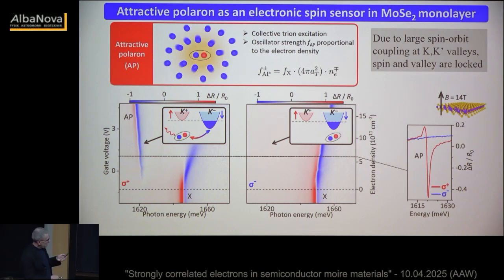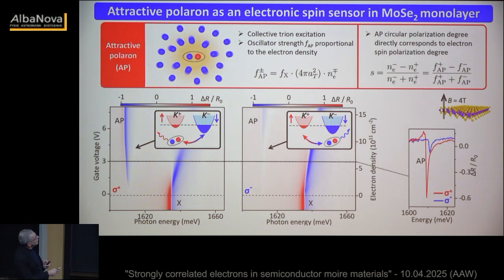There's some interaction with the electrons, but there is no bound state and there is no attractive polaron resonance. Okay? Now, if I didn't go up to such a high field, then, say in this case four Tesla, there will be some electrons in the other valley. Then I see the attractive polaron in both valleys. And now, what I can do is integrate and find out the area under these transitions. For that, I need to do a transfer matrix calculation. But when I determine the oscillator strength of the two polarizations, if I normalize it, that directly gives me the degree of polarization. So it's a quantitative measure of the degree of spin polarization in the system, irrespective of the magnet.